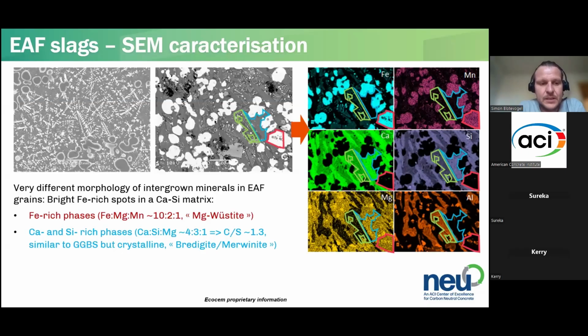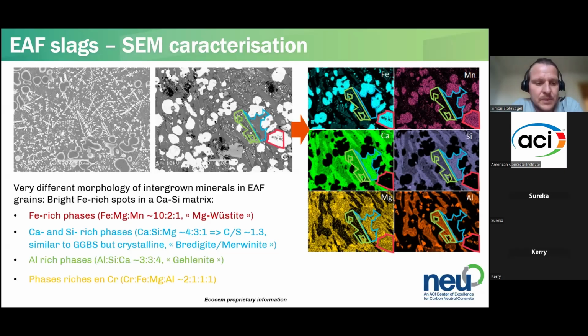We would have calcium and silicon rich phases that are mostly merwinite or bredigite, so C2S structure with some magnesium inserted into there. And aluminium-rich phases, which are mostly gehlenite or some melilites if we mix in magnesium, but that usually doesn't happen so much. And we have most of the time some spinels, especially in recycling or high scrap metal using EAF slags, that are spinels with a high ratio of chromium in there.